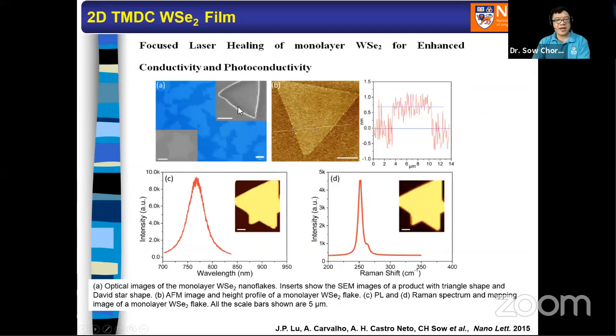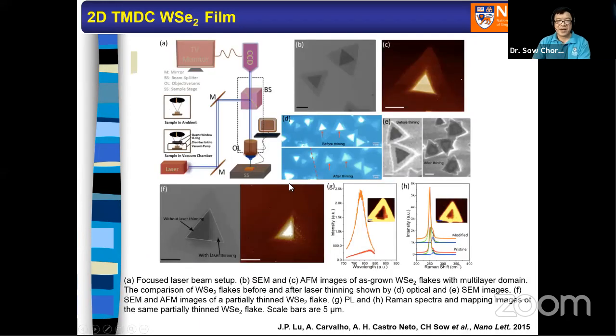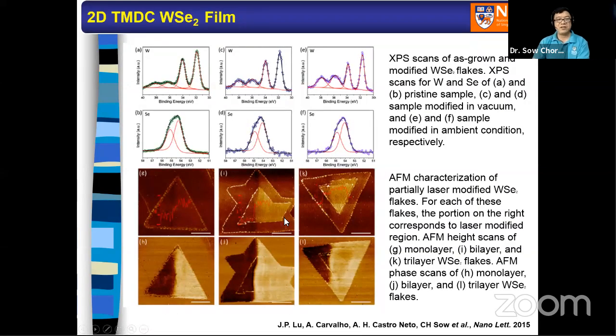So here are all the standard characterizations. WSe2 is grown in this triangular form, and we can use a laser beam to modify it. This picture shows the right-hand side of the triangular-shaped WSe2, where multiple layers have been modified. Then we can characterize them using AFM and XPS, to show that indeed the process of laser modification changes the chemical composition, with a lot of oxygen added to the system. And in this particular case that is actually good. I would like to stress that not all laser powers work; there is a certain window whereby this will work well. Otherwise, it either doesn't work or you destroy the sample.